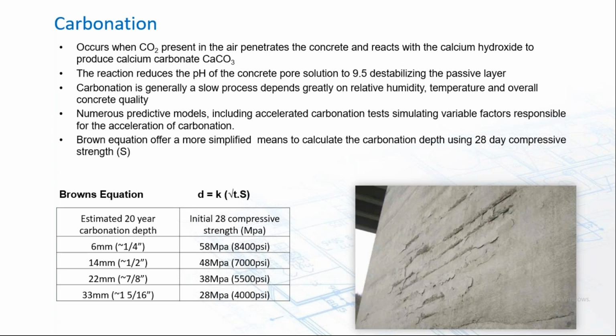Carbonation is the first one, and that occurs when CO2 naturally occurring in the atmosphere penetrates the concrete and reacts with the calcium hydroxide in the concrete, and that produces calcium carbonate, or it essentially turns the concrete to chalk. The reaction reduces the pH of the concrete pore solution, destabilizing that passivating layer. Carbonation is generally a very slow process and depends greatly on relative humidity, temperature, and overall concrete quality.